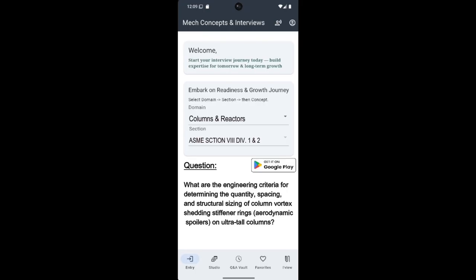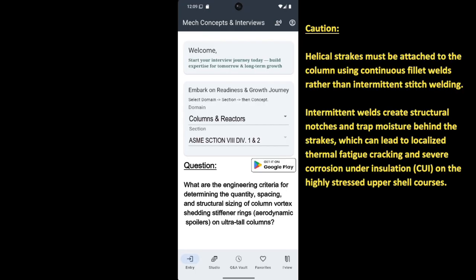And what is your detailed metallurgical caution regarding the welding of those strakes? Wind loading implies constant dynamic stress. The welding protocol must be flawless. Helical strakes must be attached using continuous fillet welds. Not stitch welds. Exactly. Some fabricators try to save time by using intermittent stitch welding. That is a critical error. Intermittent welds create structural notches and moisture traps behind the strakes. And under dynamic load, that's a disaster. Under continuous wind loading, those notches act as stress concentrators, initiating localized thermal fatigue cracking. Furthermore, the trapped moisture leads to severe corrosion under insulation, or CUI, on the highly stressed upper shell.